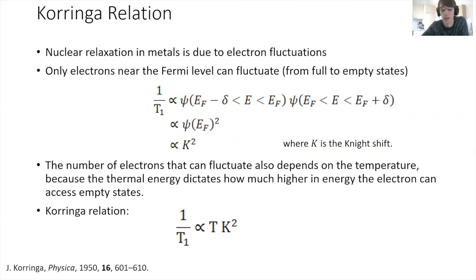Indirect Knight shifts are more complicated. They also depend on the density of states at the Fermi level of whatever your valence orbital is, because that tells you how much Pauli paramagnetism you have in the first place. Or put another way, it just depends on the Pauli paramagnetic susceptibility. But then it depends on your core orbital electronic structure, and actually this has been tabulated, because the cores of elements are pretty well understood, and so you can just look up in a table the conversion factor: what orbital do I have in the valence, and how much effect would I expect for each of my different core s orbitals?